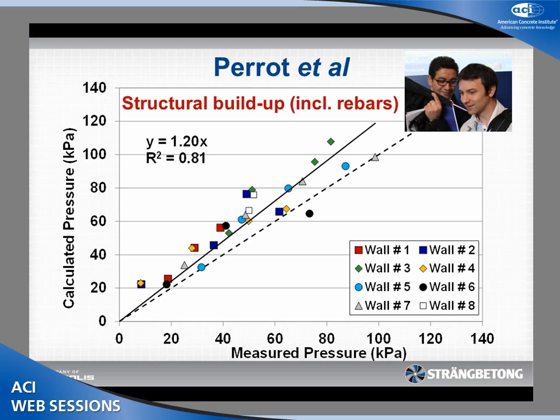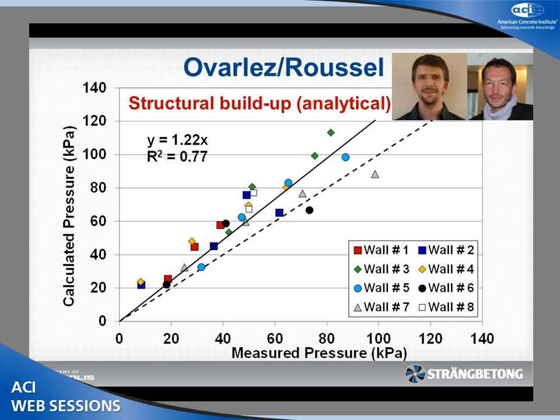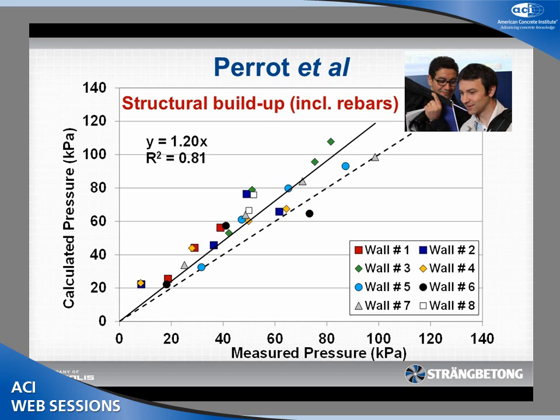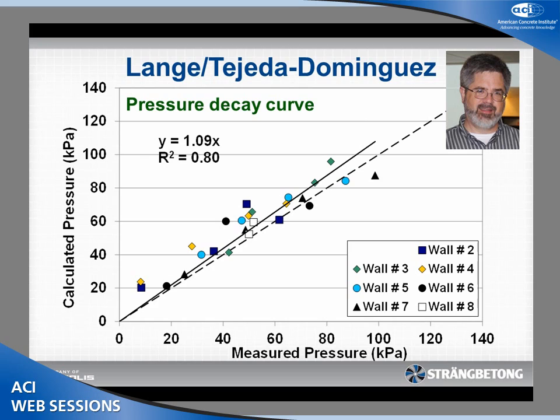The other French group incorporated the influence of the rebars. Many of those models consider friction between formwork and concrete, relating to shear stress. If you have a lot of reinforcement, the concrete has even more chance to get stuck. They based their model on the structural buildup framework and added parameters relating to the rebars. The result is slightly higher precision and a lower slope. David Lange's pressure tube approach results in the smallest slope, very close to the one-to-one line, and a very good R-squared of 0.80.